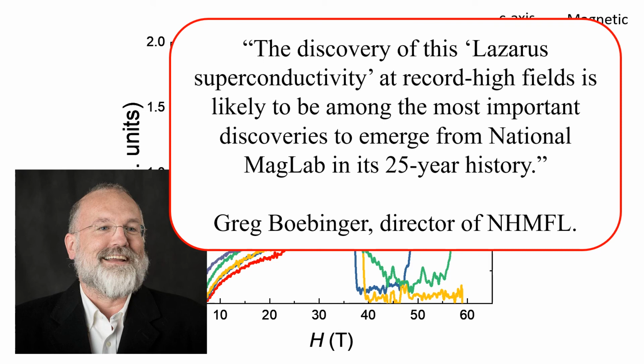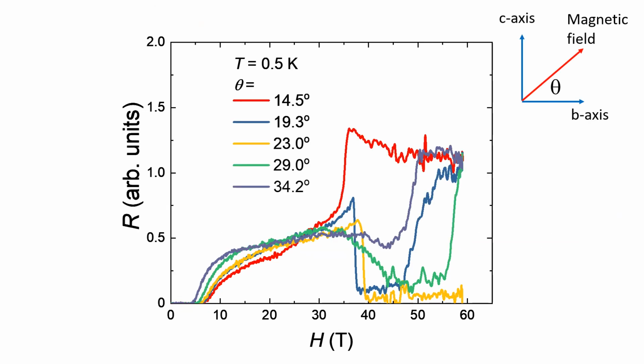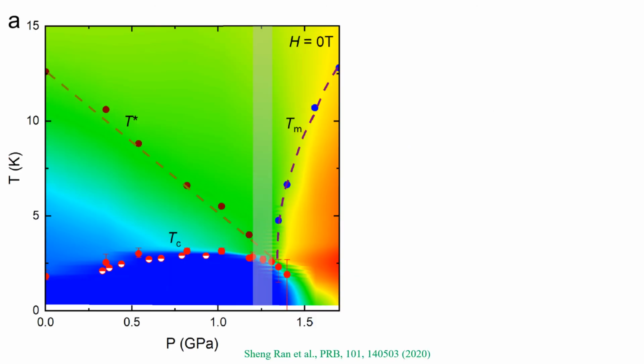Okay, I promised there are 3 such phases. Well, where's the third one? The first 2 are at ambient pressure, and the third one is under applied pressure. Here's a phase diagram of uranium ditelluride under pressure. Now, first we see the superconducting transition temperature is enhanced by twice. In the normal state, in the low pressure region, we observe the suppression of an energy scale that might be related to Kondo coherence. In the high pressure region, we observed a new phase with magnetic nature. It could be a ferromagnetic phase.